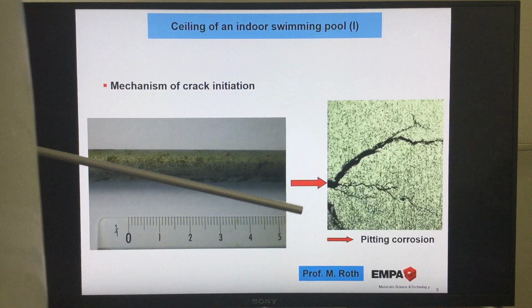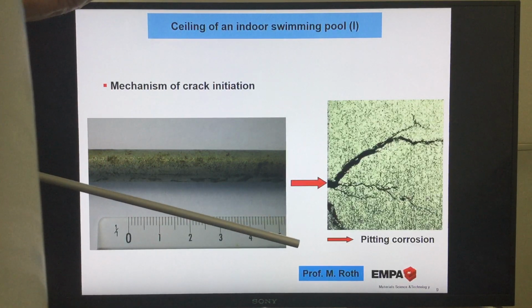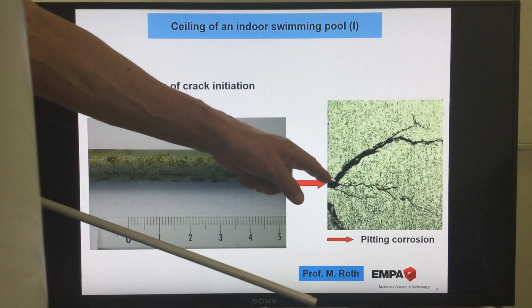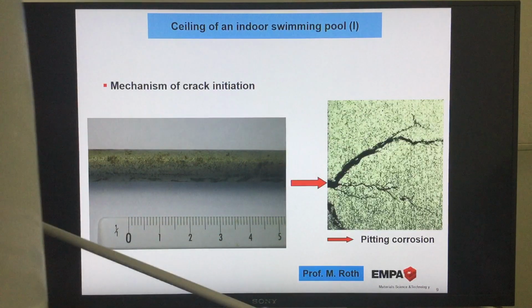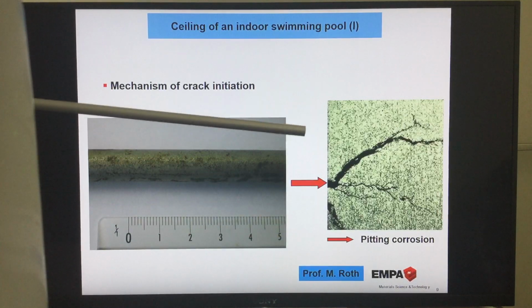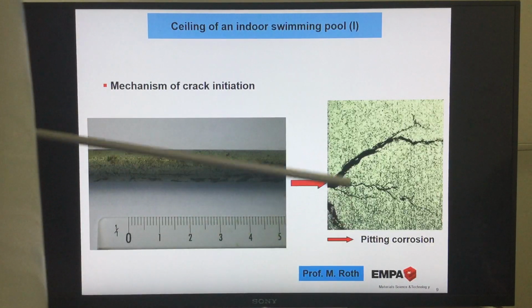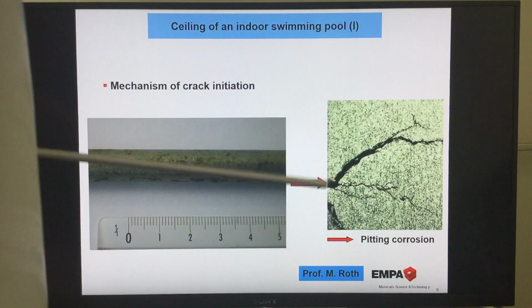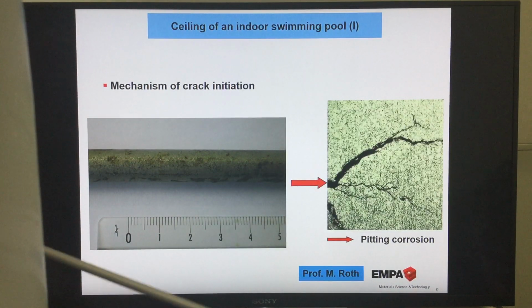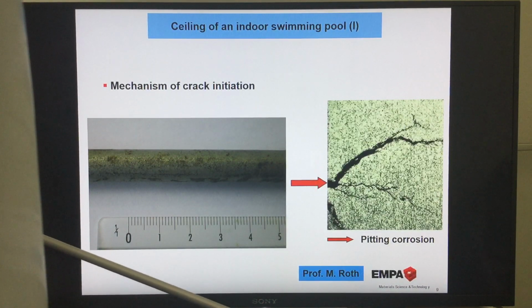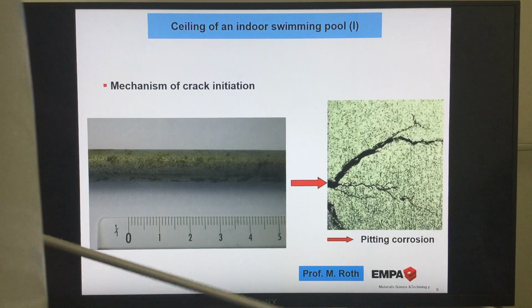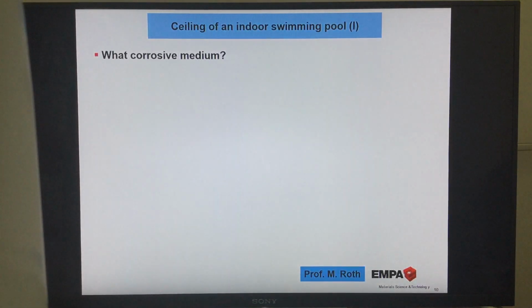You have a higher stress intensity at this crack, at this hole, and from there then the cracks start inside. So there's both a chemical effect and a mechanical effect together, and they made this. And of course we had a lot of time. We have 13 years available. It's a time-dependent process also.